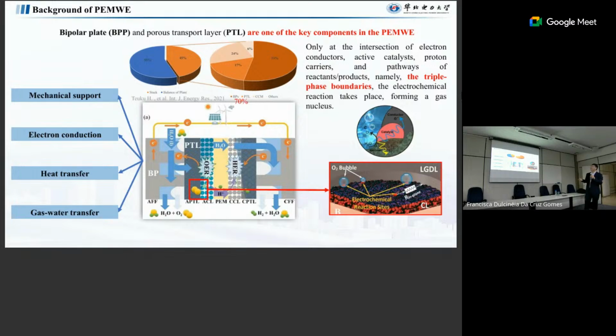So for the whole system, for the electrolyzers, we get the membrane, then we put on the catalyst. Then we put the PTL and the bipolar plate. Then we have the stack. But afterwards, people think, if we want to reduce the cost, we have the balance of plant. With one stack, the balance of plant is comparable. But if we have 2 stacks, then we need twice the balance of plant. If we have 3 stacks, we again need a lot. So we think, if we make one stack bigger, then we reduce the cost of the balance of plant. That's why today we try to make the electrolyzer bigger and bigger. In China at the moment, for alkaline, we can get 2,000 cubic meters per hour. Really big.